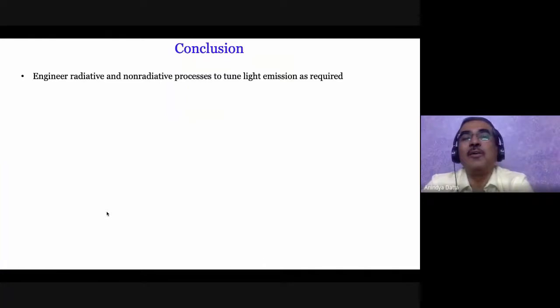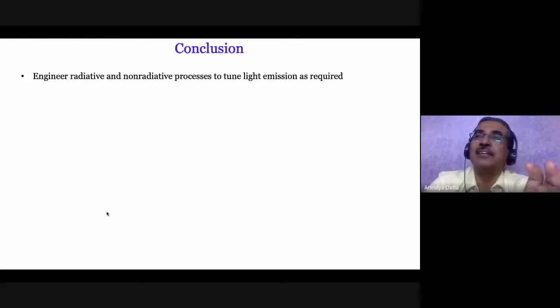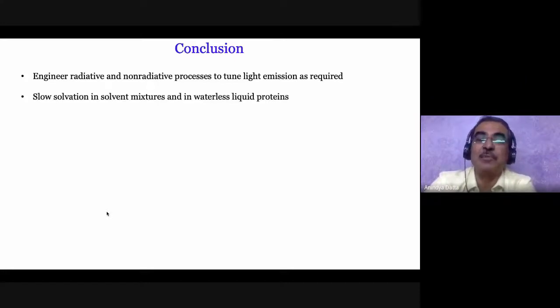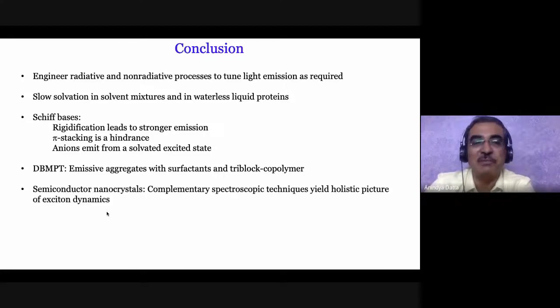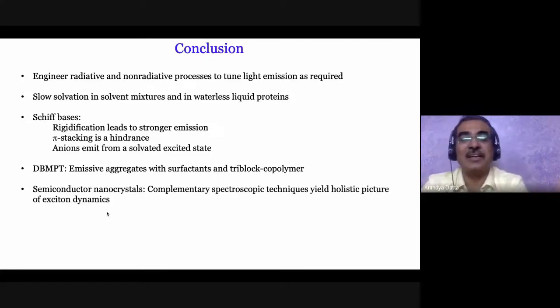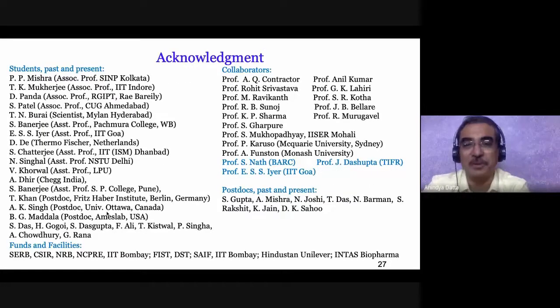To conclude, we try to engineer radiative and non-radiative processes, and we try to get light, or we try to tune light emission as and when we require. Using it, the processes that we have studied are slow solvation in solvent mixture, which is an interesting phenomenon because this is not really something that has the surface of protein or any such thing. And also we see similar slow solvation in so-called waterless liquid proteins. I have not talked about Schiff bases today, I have not talked about DBMPT. In semiconductor nanocrystals, we have established the fact that using complementary spectroscopic techniques, one can actually generate the entire picture of what exactly is going on.